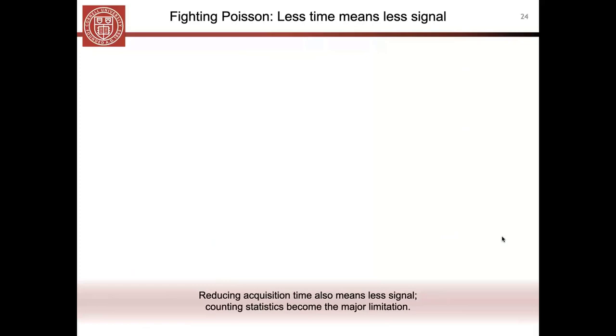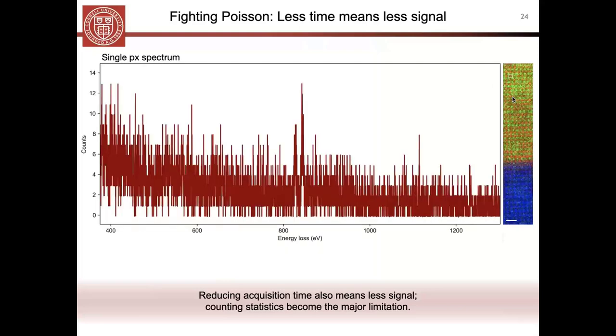And so, really when it comes down to it, you can outrun the drift and you can run your experiment faster. And if you have a fast detector, of course, that helps a lot to reduce the drift. But when you do cut down the time, you're also cutting down the total signal. And so if you go back to this cryogenic EELS map that I've already showed you, if we look at, for instance, one lanthanum atom that came out somewhere from this upper corner, if we look at a single pixel from a lanthanum atom, you get a spectrum that looks like this, right?